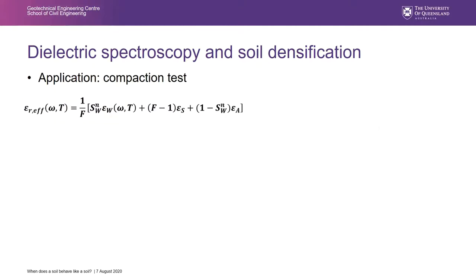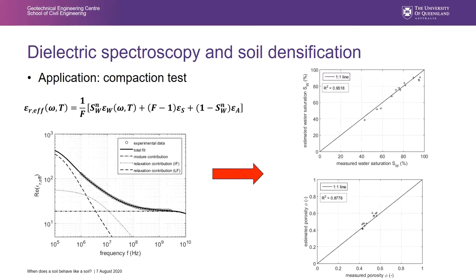So what we've been doing is using this model in optimization to fit the spectrum very properly. And based on this model, we're able to estimate water saturation. As you can see, with a very good accuracy for saturation, a good accuracy for porosity, but a little bit less. This is a very cutting-edge method because we're able to simultaneously estimate saturation and porosity.